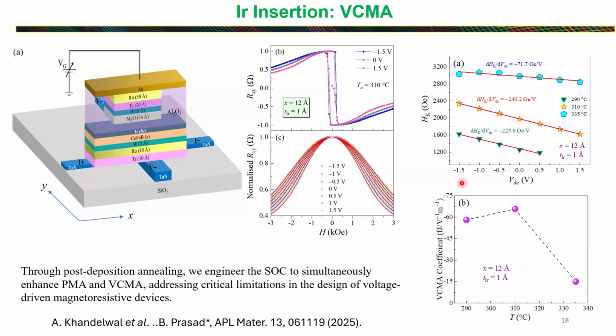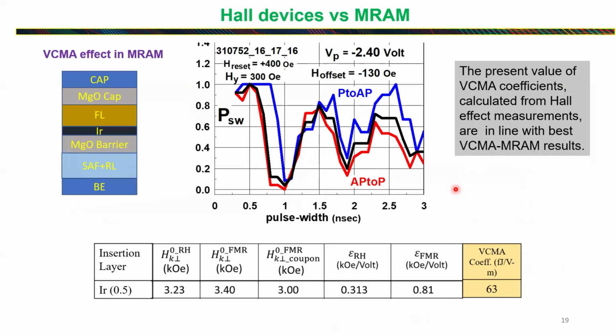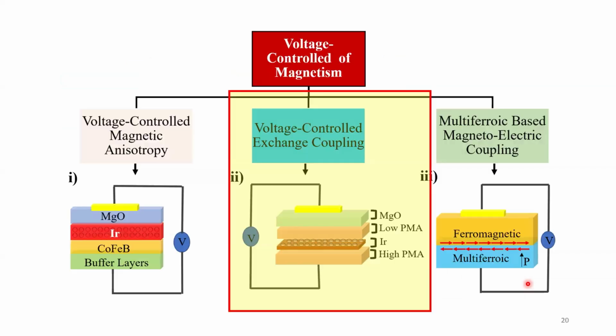One can increase the PMA and VCMA. We have been doing a lot of other insertions and a lot of other interesting work, but only this work has been published so far. That's why I'm showing only this work today. We also cross-checked our Hall bar device performance with the MRAM. We found that the VCMA coefficient you get from Hall bar devices comes pretty close to what you get from the MRAM stack. So whatever we get in the Hall bar devices can be translated to the MRAM structure.